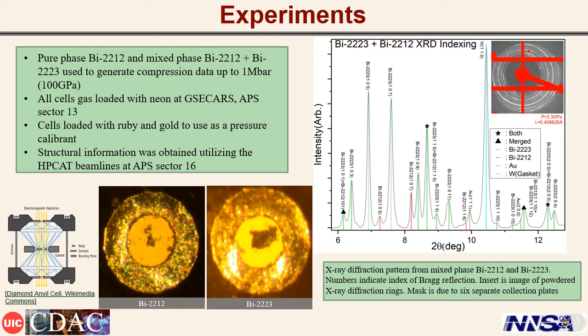Samples were brought up to 100 gigapascals, about a megabar, with X-ray diffraction patterns taken every 2 to 3 gigapascals at HPCAT, which is APS Sector 16. Both mixed phase and pure phase patterns were refined to generate compression data.